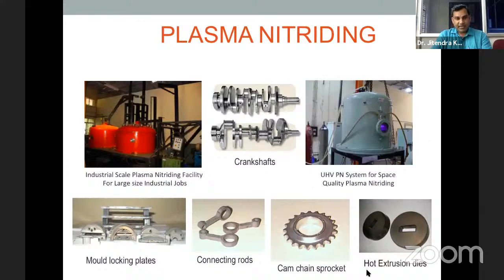So crankshaft and connecting rod, cam, hot extrusion dies, mold locking plates, all are surface hardened by this plasma nitriding. So this is the equipment where you have a vacuum chamber, and you can see that the plasma is generated inside it, and that plasma makes the surface of these different kinds of material harder. So this is the experimental setup, and this is how a plasma nitriding facility looks in industry.